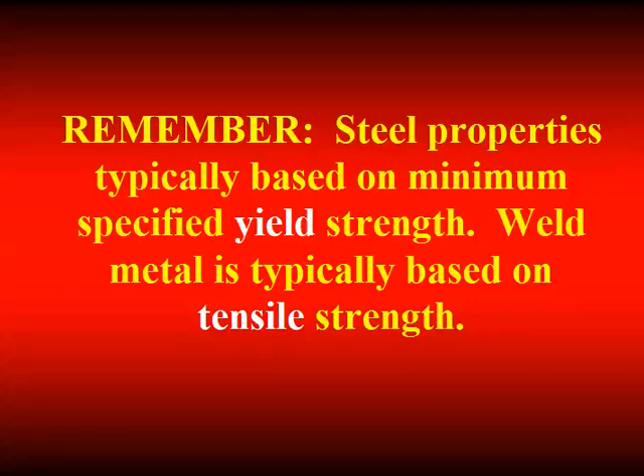Remember, steel is typically specified based upon the yield strength of the material. We talk about grade 50 material, and that's 50 yield, right? When we talk about grade 70 weld material, that's tensile strength. I won't get into the reasons and whys behind that right now, but that's a point of confusion oftentimes. 70 will be the tensile. Associated with 70 is a yield strength, 58 KSI, and 58 to 50 is about matching, and that's why we consider 70 weld metal to be matching on 50 steel.